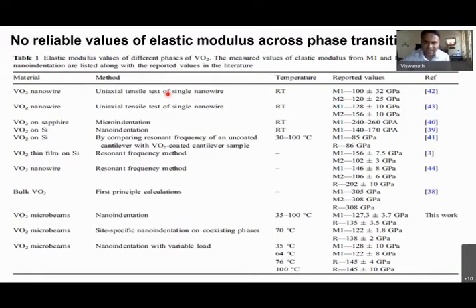So we also looked at the literature. Interestingly, though this material has been known for 60 years now, for the actual mechanical properties of vanadium dioxide there is a huge scatter in the values. You will find the elastic modulus from as low as 70-80 gigapascal to around 300 gigapascals by first principle studies and so on. In fact, there are only a few studies. Most of the measurements are limited to the room temperature monoclinic phase. Only a few studies are there for the high temperature phase.